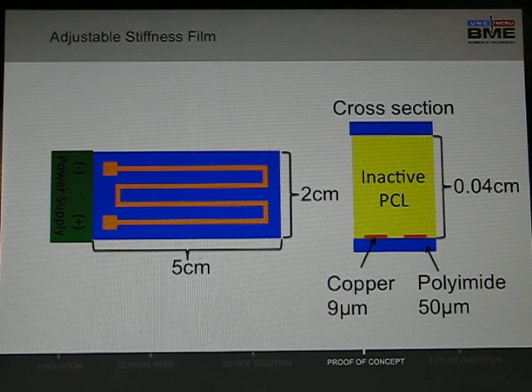Here we show a schematic of the first embodiment of our device called adjustable stiffness film. It measures 2 cm by 5 cm with a thickness of approximately 400 microns. The cross section we show in yellow is the inactive PCL or solid PCL. This layer is sandwiched by a higher melting point polyimide shown in blue. We etch out a copper path, and when we connect a power supply, the current passes through the copper path. Through resistive heating of the copper, it causes the inactive PCL to melt and become what we define as active. This short animation shows an inactive PCL going to active PCL when the current passes.